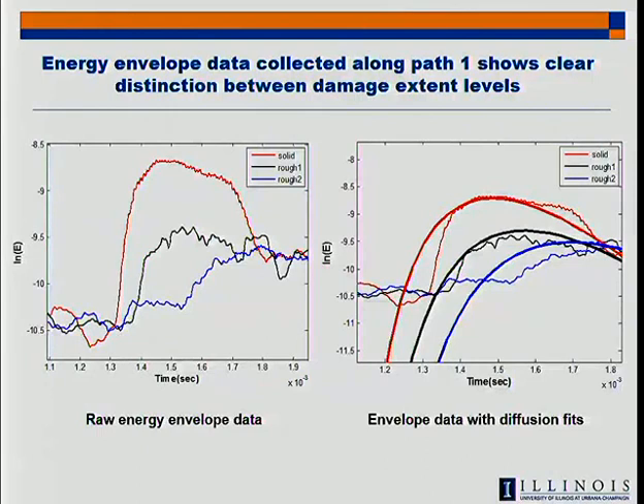But here you see from path one, which skims right alongside the end of that rail seat collar, we see the three cases, solid, rough one, and rough two. So you can see the increasing damage follows that diffusive trend. And again, it's not real diffusion, it's not heat diffusion or material diffusion. They use diffusive equations to fit these lines, and from that they pull a diffusion coefficient, which they relate to damage. It has nothing to do with actual diffusion. And that confuses a lot of people, and that's why I want to spend some time. But when we fit the lines, we can now quantify this difference and have one diffusion coefficient for this level of damage and this one, and they are distinct from each other.